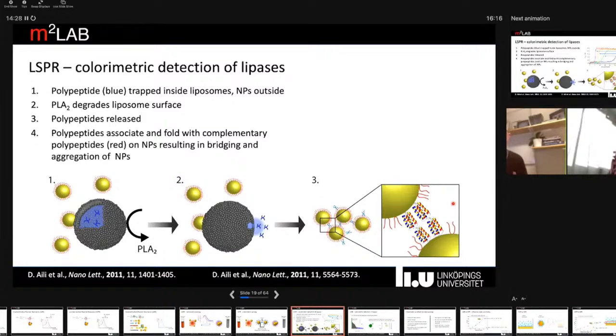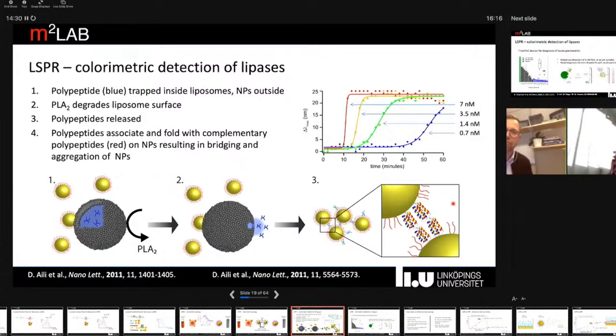And we can monitor this, essentially a redshift of the plasmon band, which is shown here on this axis. And then we monitor this process over time, and we can see that we can get slightly different magnitude in shift depending on concentration, but above all, the higher the concentration or activity of this enzyme, the faster is this release.